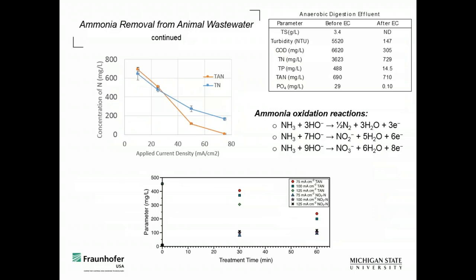And so we did this in poultry processing water. And so as you can see here, here is as a function of current density in these poultry processing waters. Here we start out with total ammonia nitrogen and total nitrogen. So as you can see, almost all of the nitrogen in there is ammonia. And then they said this is a function of current density.